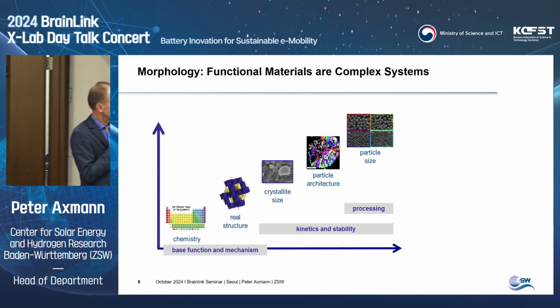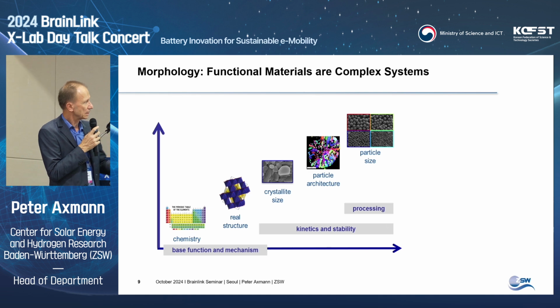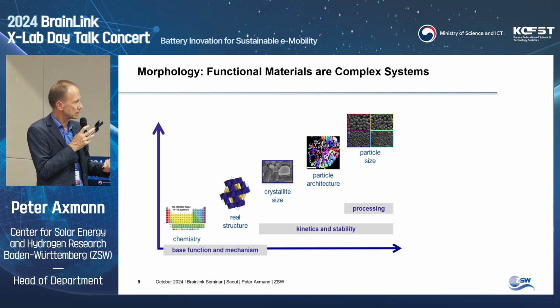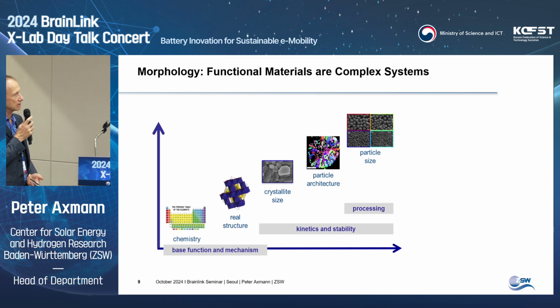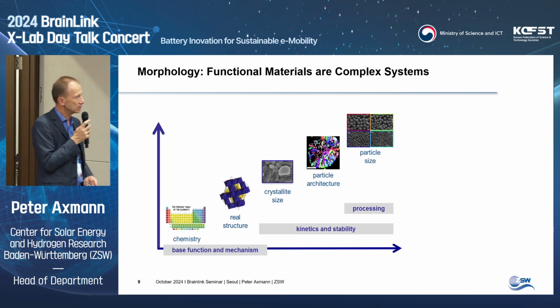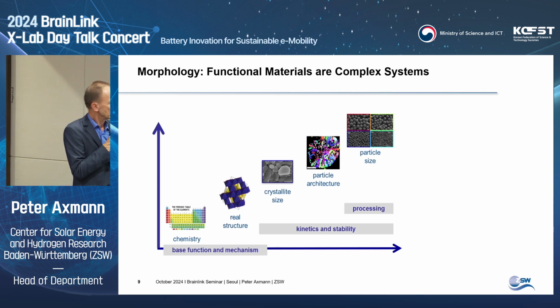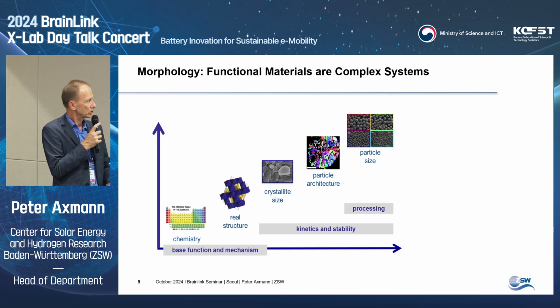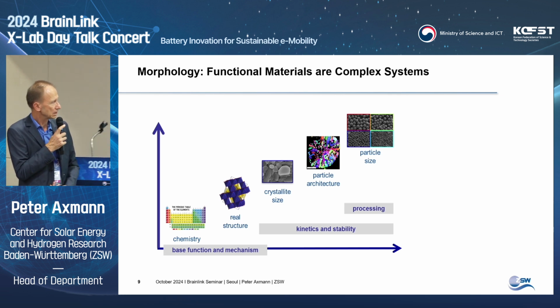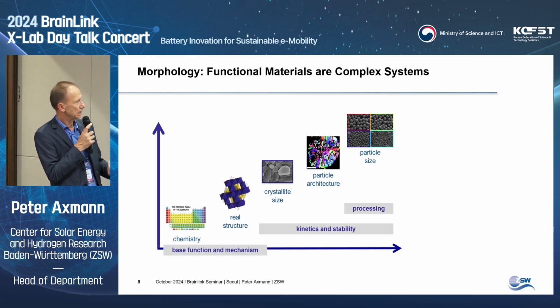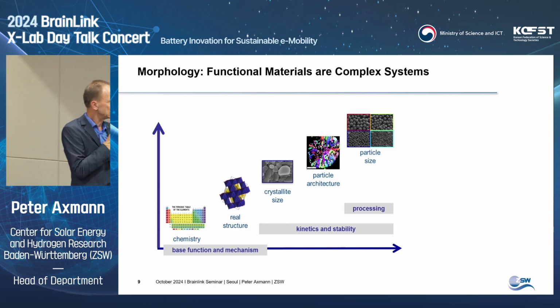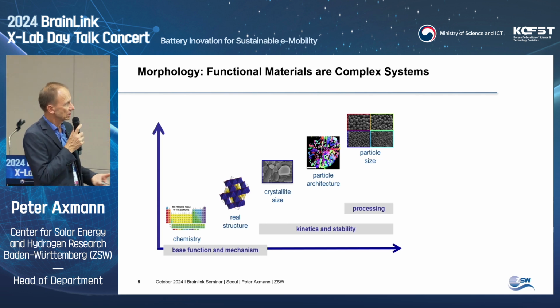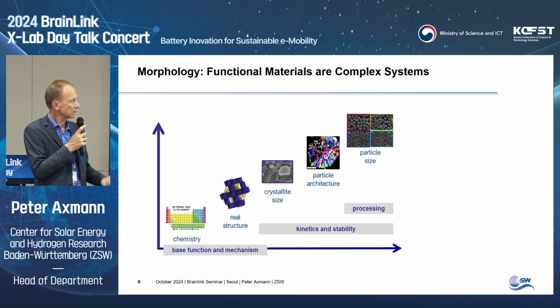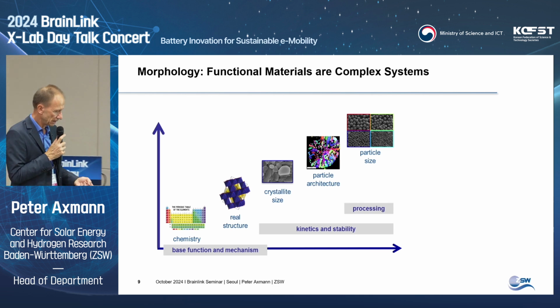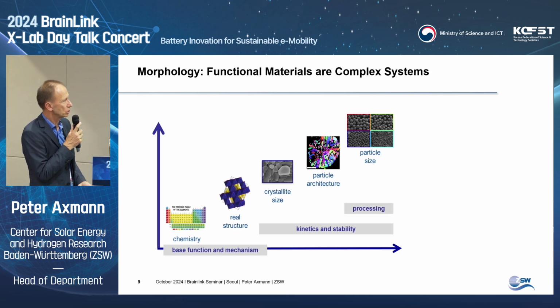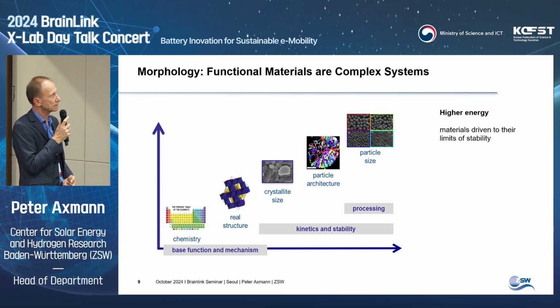the real structure has 3 dimensions. You have a crystallite size, which might be larger or smaller, and this has an influence on the kinetics and on the stability of the materials. And these crystallites are then arranged in 3-dimensional structures like particles, and this particle architecture as well has an influence on kinetics and stability. And finally, these particles have a certain shape and a certain size distribution, and this has an influence on the processing behavior, which you finally need for going to larger cells.